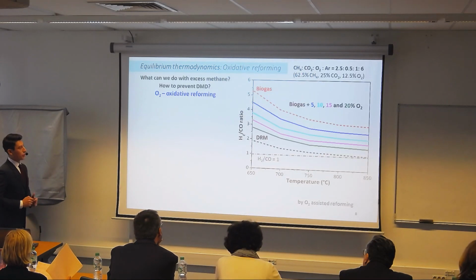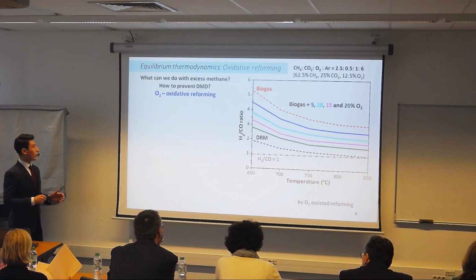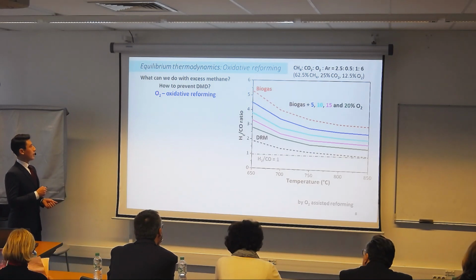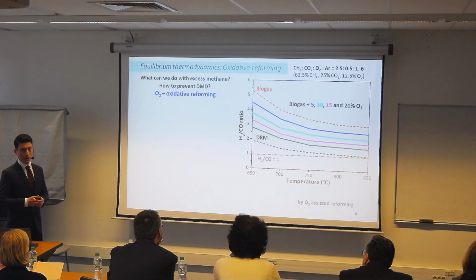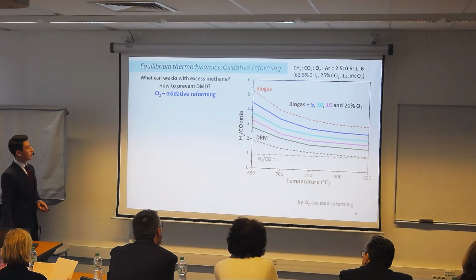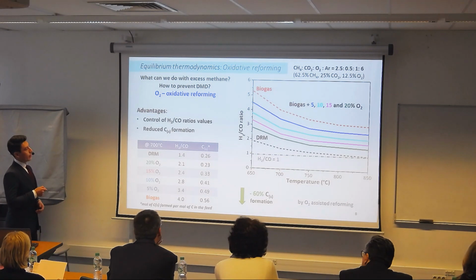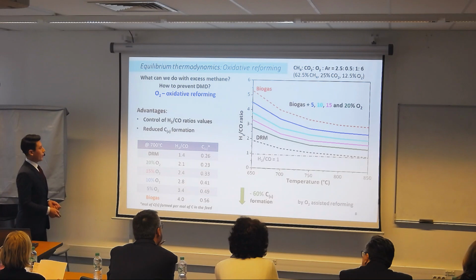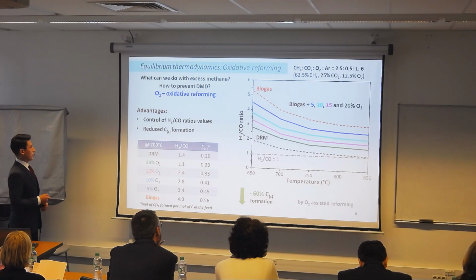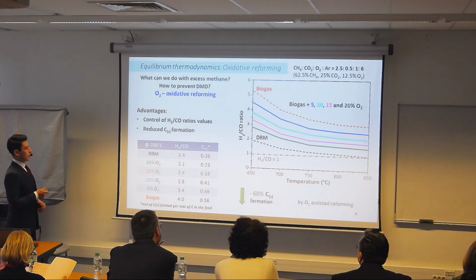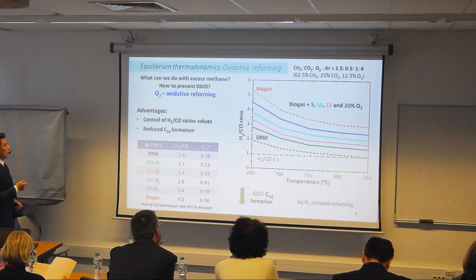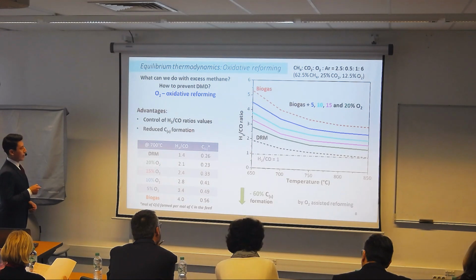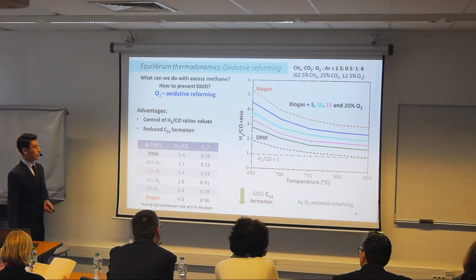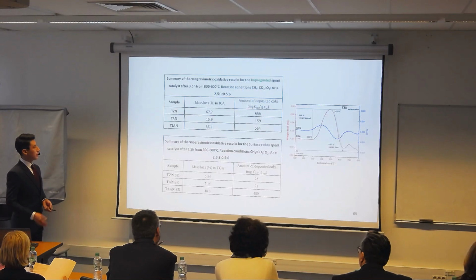So as I previously showed, we have carbon deposition on the catalyst. What we can do, as has been reported, is oxidative reforming, which can decrease the carbon deposition and therefore the deactivation of the catalyst. In this plot, you can see I forecast different percentages of oxygen in order to know the effect on the syngas ratio. We can see that as we increase the percentage of oxygen, we have control of the syngas ratio values, and we are reducing the carbon formation. Theoretically, we have around 60% less carbon deposition in the system with oxygen.